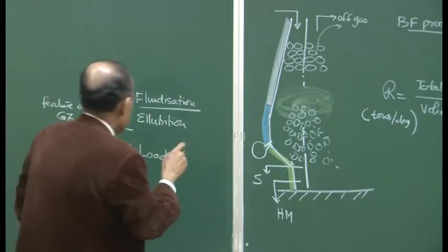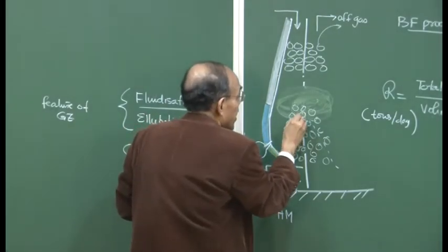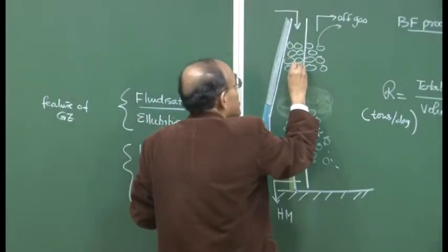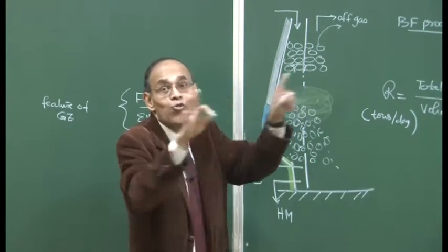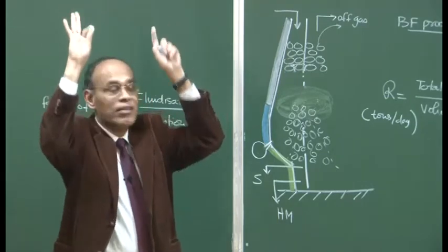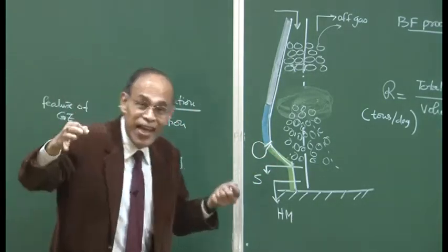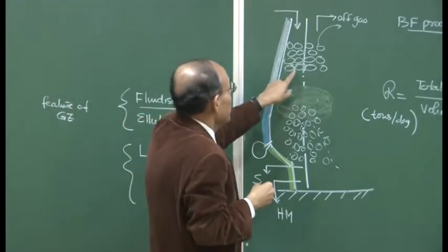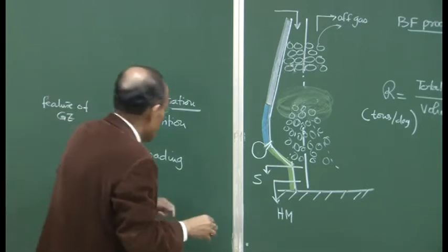Loading refers to the point when liquid has stopped flowing down through the bed of solid-liquid mixture, because the upward drag counterbalances gravity on the particles. If you flow still more gas, the liquid can travel upward — carried by the gas — enter upper passages, and at lower temperatures solidify and seal those passages. The gas then cannot flow up, because all available pores in the granular region have been choked. That phenomenon is known as flooding.